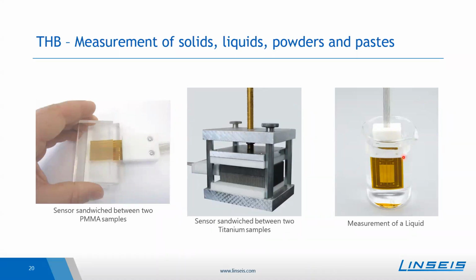The sensors are Kapton foil sensors. So it is a Kapton foil where in between two foils, the heating wires are located and everything is closed. So the sensor is basically just a Kapton foil, so it can be cleaned very easily. For that, one can use some standard solvents like acetone, isopropanol, or some other alcohols, for example. So you just wipe the Kapton foil so that it will be clean again.